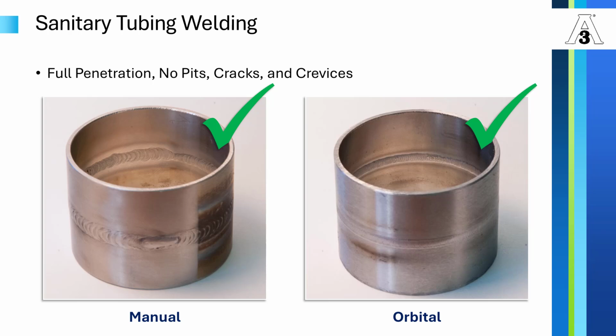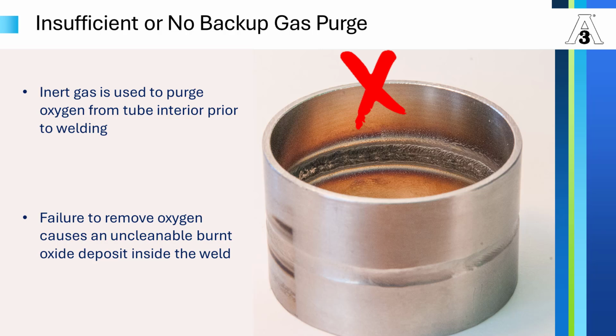We saw these yesterday, good welds. I'm not going to go over that again. This is an example of almost no purge. I was asked this, how does this happen? This happens a lot in place welds, like on long pipelines. You put a long pipeline up and say it's running a couple hundred feet, and you've tacked everything together, and you've done good tack welds, and then you have to purge that line of all the oxygen, which means you're going to hook up an argon line, you're going to put a plug on the end with an argon hose going in.